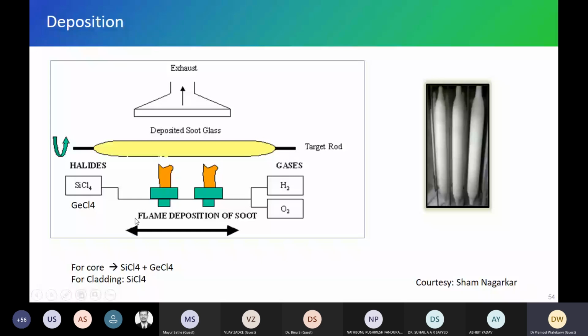So this is the soot. You can see at the right side. It is a white colored soot. Okay, its diameter is maybe 125 mm. It's a very big size, and 1 meter height. So we get such type of soot. It's called soot. Okay, I think it is clear, right, everybody? We deposit SiO2, GeO2 in small particle form. So we get the soot here. It's the first stage. And once we have this, we put it in the furnace, a hot furnace at 1550 degrees Celsius. The soot gets converted to glass, means it's a clear glass. Okay, let's see how it looks like here.